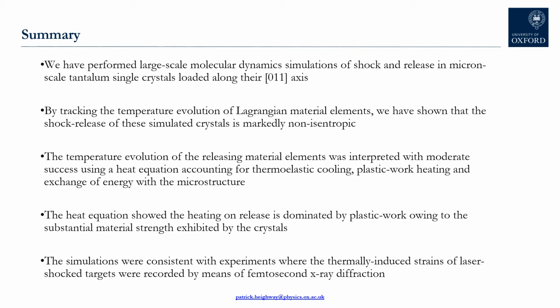That temperature analysis revealed that it is indeed plastic work heating that is responsible for the elevated temperatures, and that plastic work heating in turn is owed to the considerable strength exhibited by the crystal during shock release. And finally, we performed corroborative shock compression experiments in which we observed the same excessively high release temperature following shock release via the thermal expansion that can be measured in situ using X-ray diffraction.